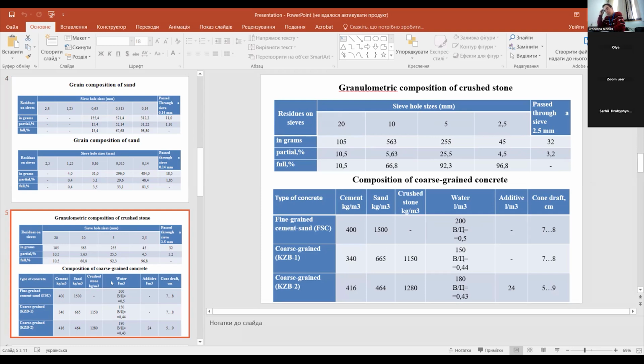The dimensions of the prism samples were 4 by 4 by 16 centimeters for fine-grained concrete, 10 by 10 by 40 centimeters for coarse-grained concrete of the first type, and 15 by 15 by 60 centimeters for coarse-grained concrete of the second type. The samples were cast in horizontal molds and compacted on a vibration table. Samples were demolded at the age of 28 days.